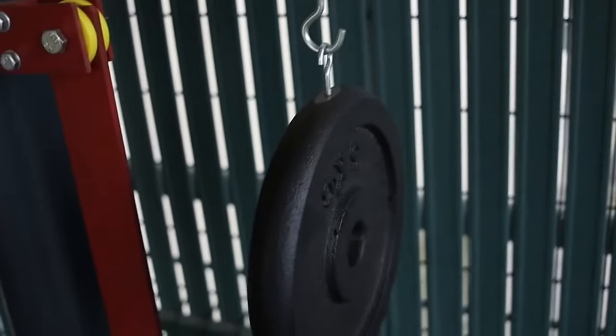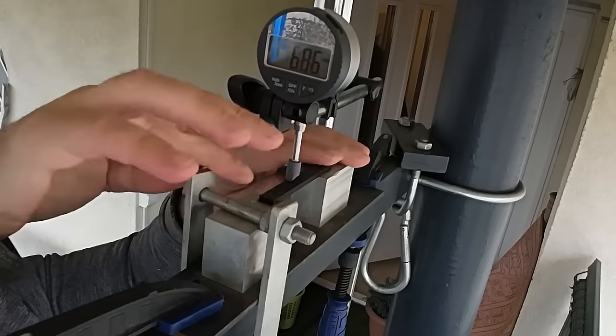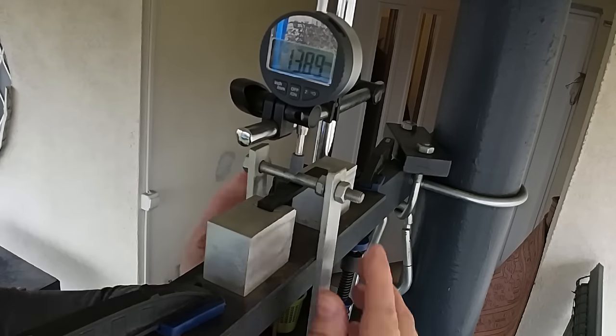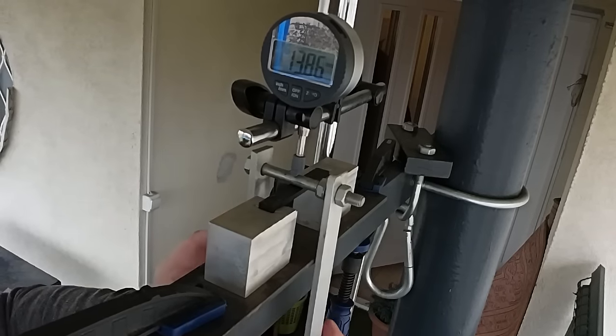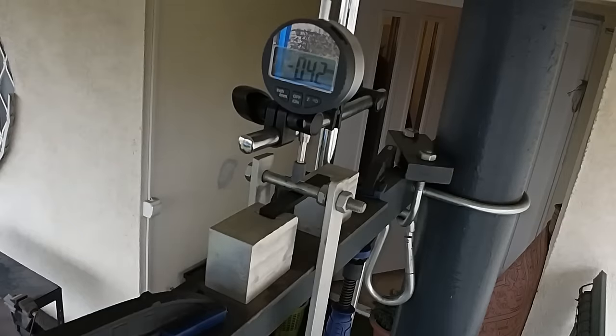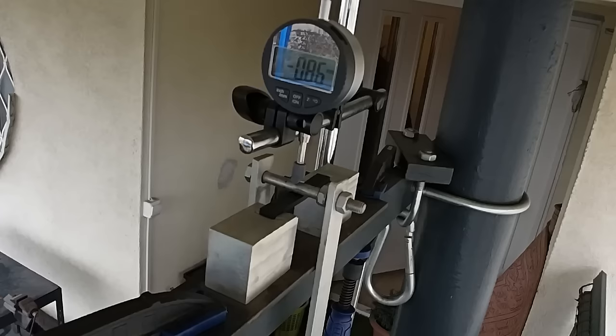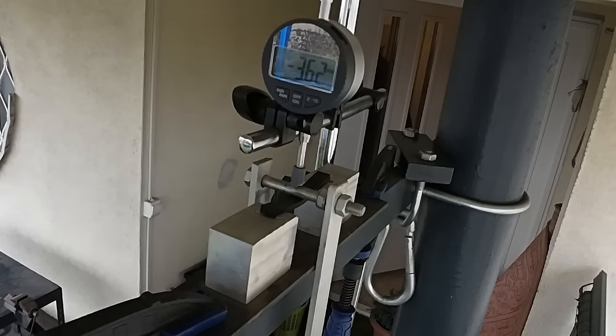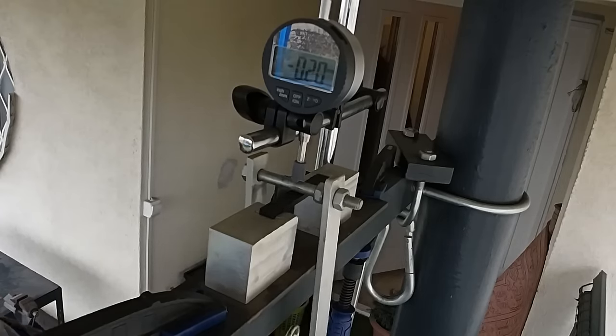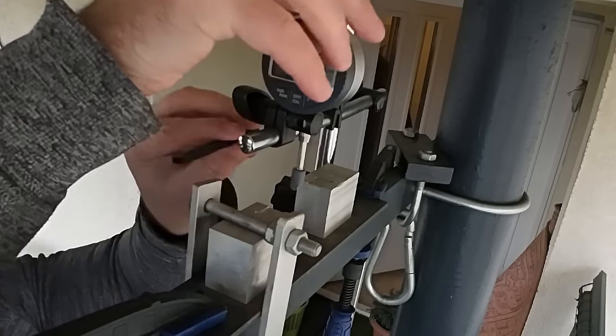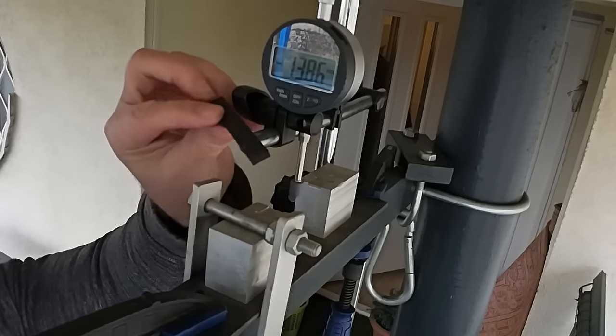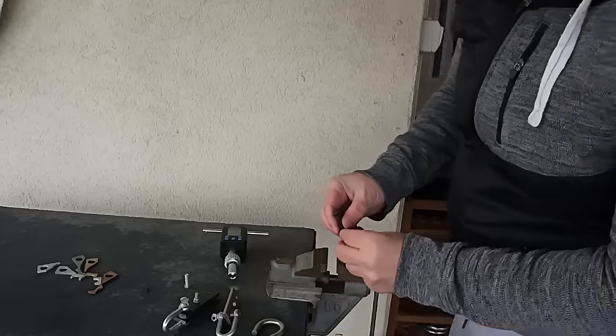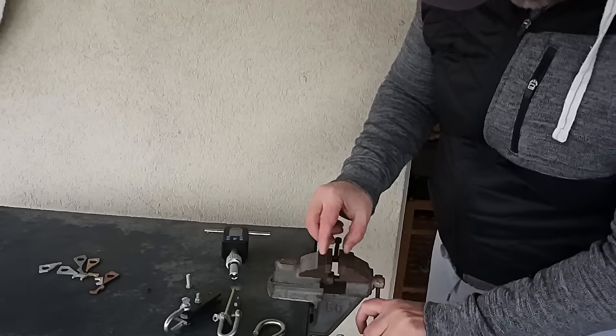Now three point bending test. Here you can see the moment where I have all load placed. And I will measure the deformation after 30 and 60 seconds under the given load. This part is speeded up 25 times. And after the test I can see very minimal permanent deformation on these test objects.